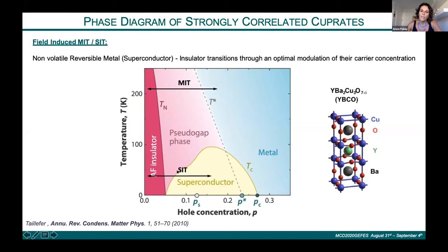And in this system, we have this phase here, the superconducting phase that arises below Tc, that in this YBCO material is 90 K. And depending on the temperature that we choose, by modulating the carrier concentration, we can induce a transition from the metallic phase to the insulating phase, or if we go below Tc, we induce a superconducting-insulating transition by directly doping the material.